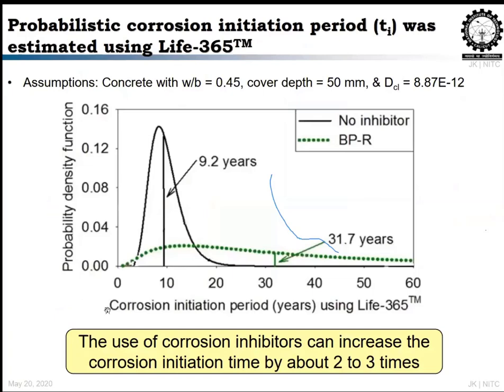And if I'm not using any PPC, just using only the inhibitors with OPC concrete, concrete which is expected to corrode in 9.2 years will, with a bipolar inhibitor, corrode in 32 years. It means almost 3 times the service life, increased because of the use of the corrosion inhibitor.